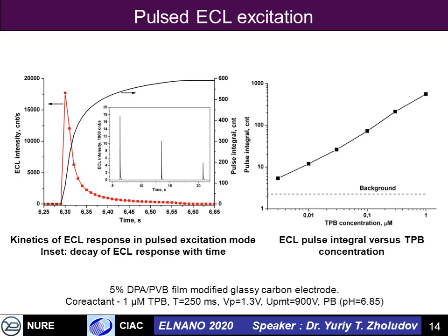Also, it was found that the stability of such films is not perfect. If you look at the inset, three consecutive pulses are given, and the ECL intensity decreases from pulse to pulse.